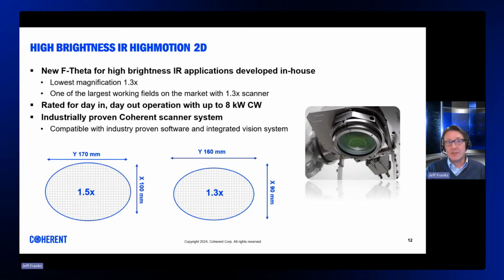New optimized F-theta optics with advanced materials, which offer exceptional focusing performance and a stable process over the entire work area, are now beginning to appear. By employing these next-generation optics on scanners, there is little or no need to make complex compensations when operating towards the edge of the welding field. Happily, we can now offer our high-motion 2D galvo with two such new optical setups, with a 1.5 times magnification and an even smaller 1.3 times. Both retain a remarkably practical field size given the tight focus spot capable.